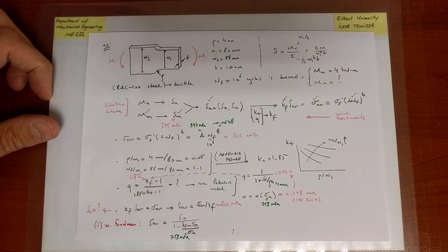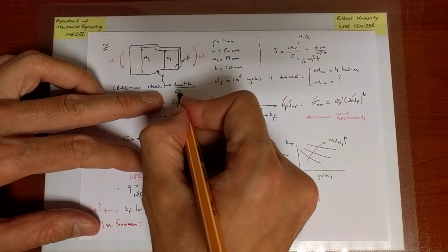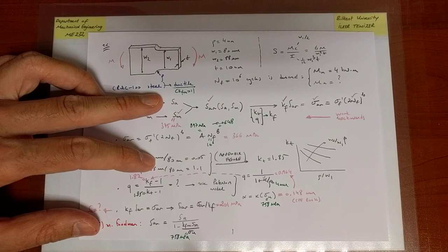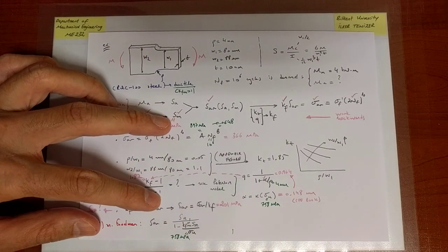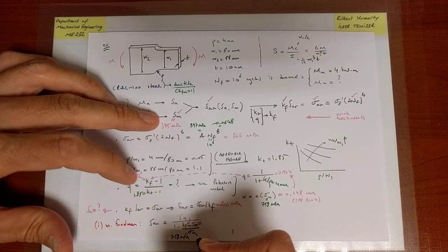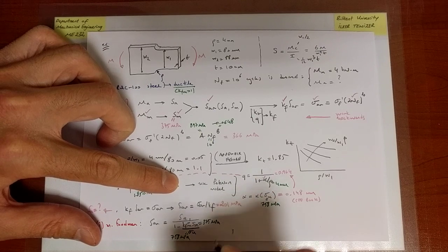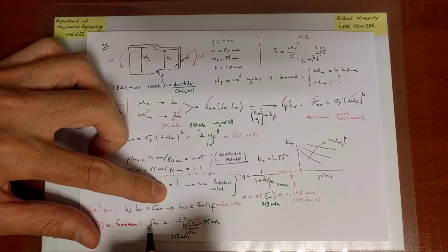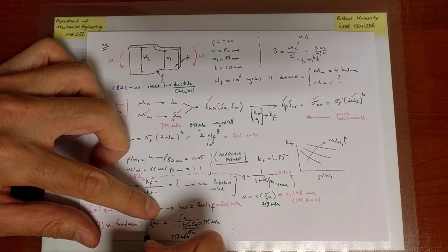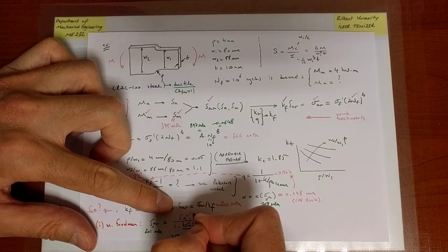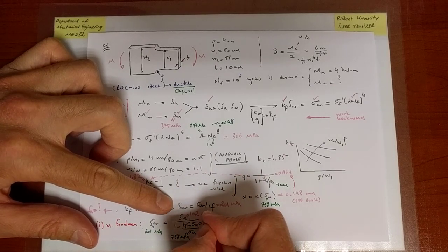It is 758 MPa. And actually we know that the material is ductile, and with that given information I will take KFM equals 1. Okay, so SM we already have calculated with the given information. It's 375 MPa, and now that we also know the value of SAR, which is 201 MPa, we can determine the value of SA, which is 102 MPa.